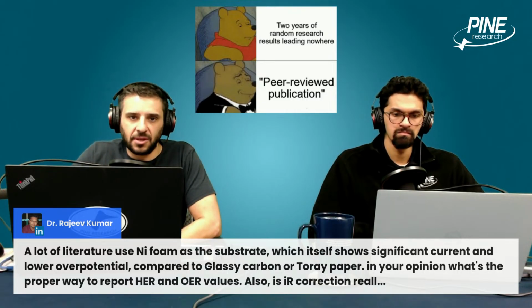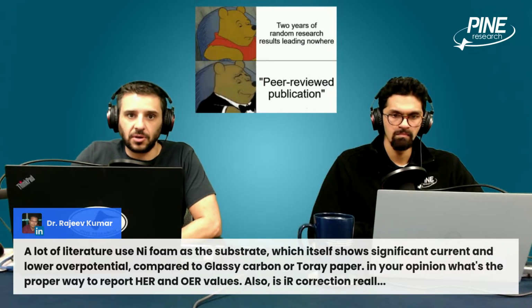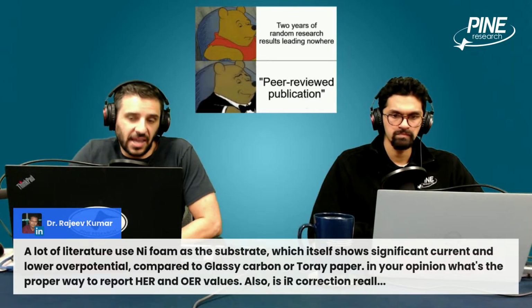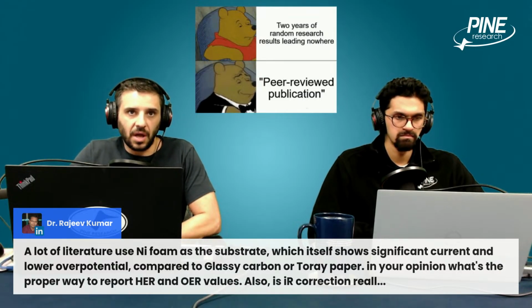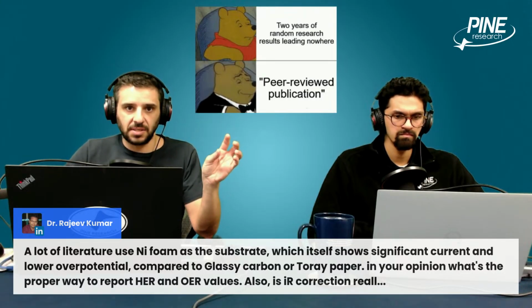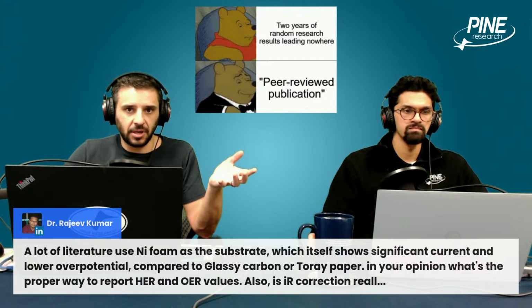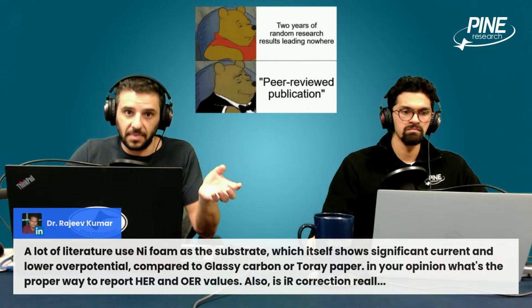but it's definitely unsure that you have perfect coverage, right? But if you're able to do that, let's say you run background scans on the nickel foam, and then you run scans with your coated material on the nickel, and you see no trace of the background, you might convince yourself that there's no nickel exposed. And then you would, again, be able to make the argument that there's no contribution from the nickel, either because its contribution to those reactions is negligible compared to your material, or because there's just no nickel exposed and it isn't even part of your electrochemical system. So those are the two things that I would say would help you.